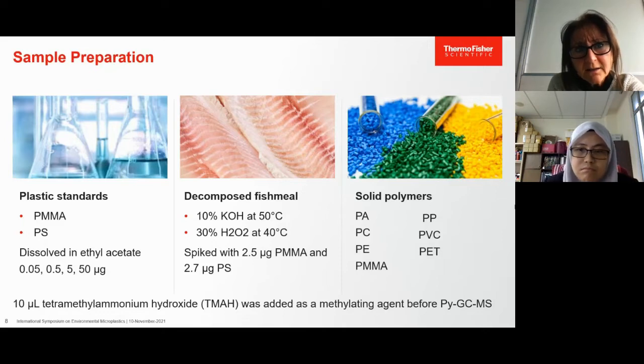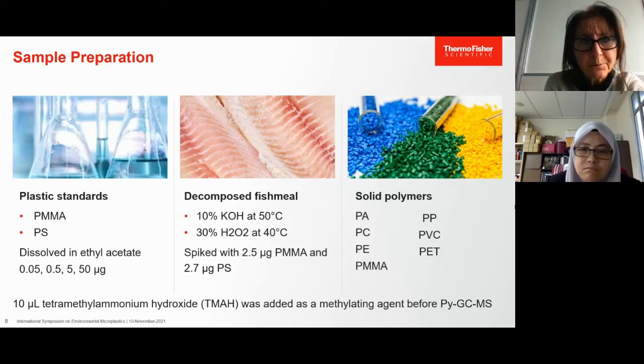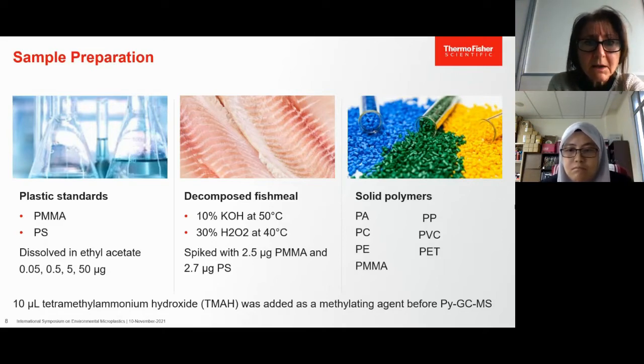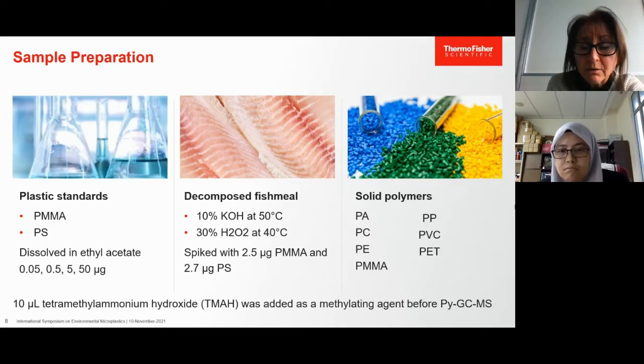To evaluate the identification capability of the system, we used solid polymer samples as listed in the slide, as single polymer samples as well as a mixture of all the polymers with 10 to 100 microgram for each polymer in the mixture. To all samples, 10 microliters of tetramethylammonium hydroxide was added as a methylating agent before analysis in order to protect polar compounds released from the pyrolysis experiments.